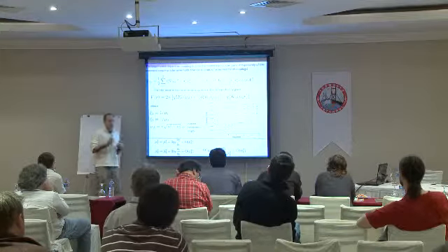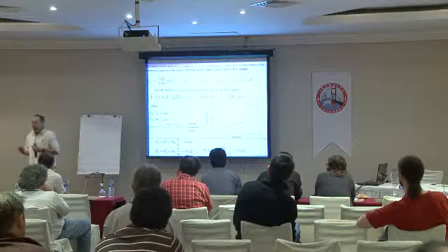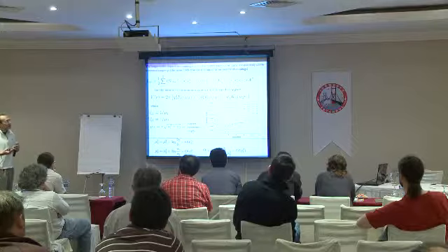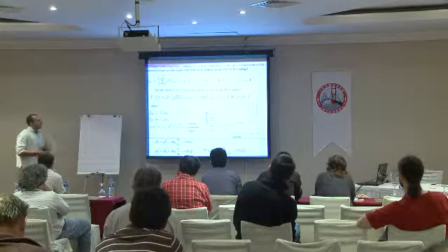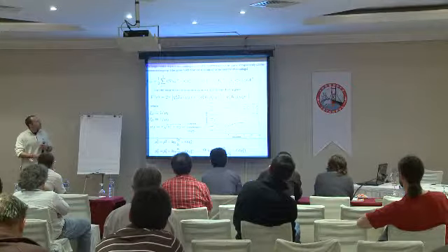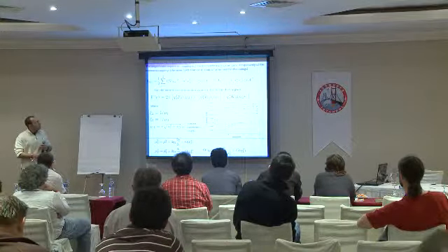So if you try to set up some equivalent of how a coherence length is defined in Tinkham for a single-band superconductor, and do the same procedure here, we should linearize our theory around the ground state. Let's write the linearized two-component theory for small perturbations of fields around the ground state.